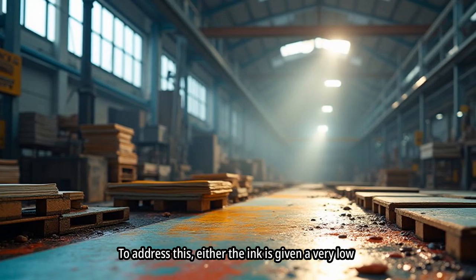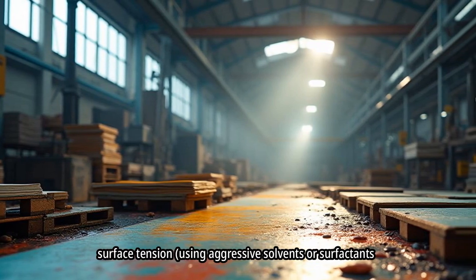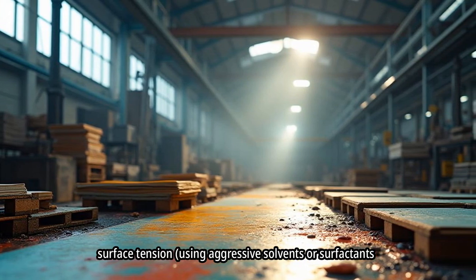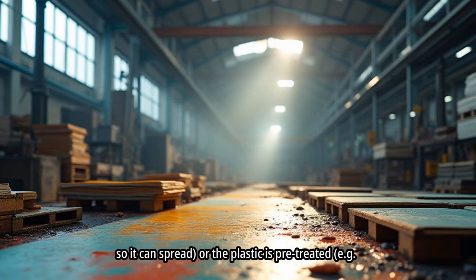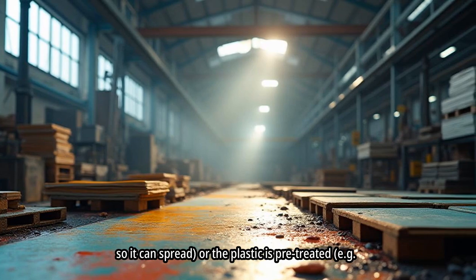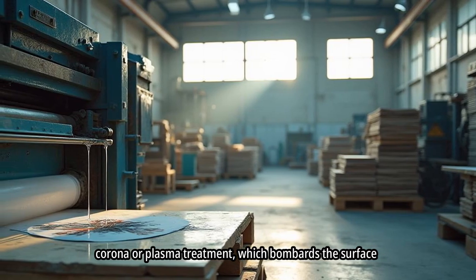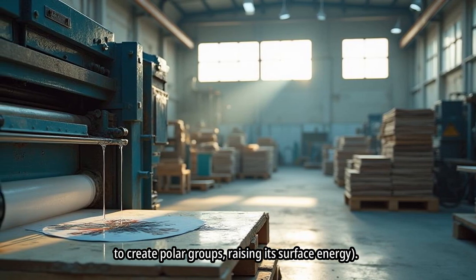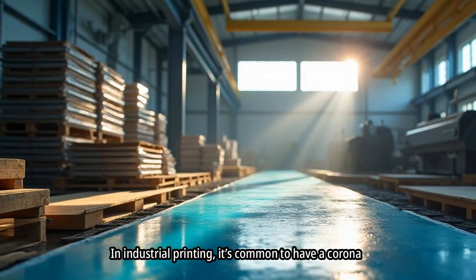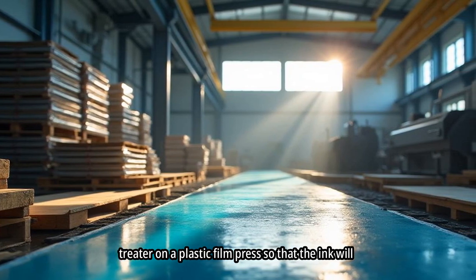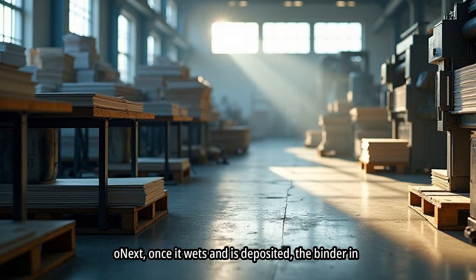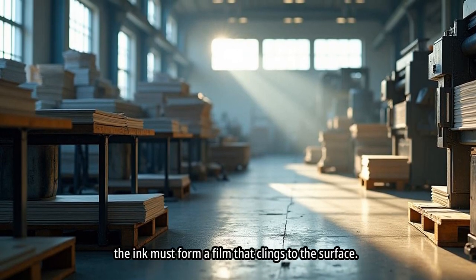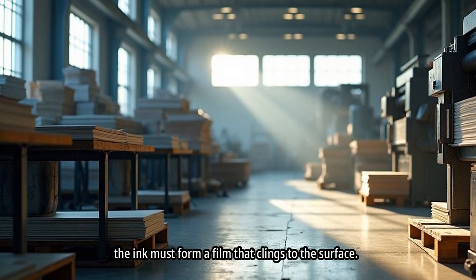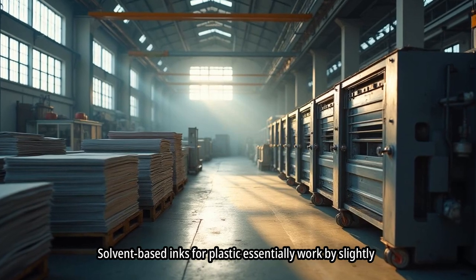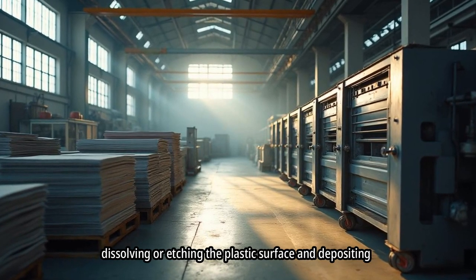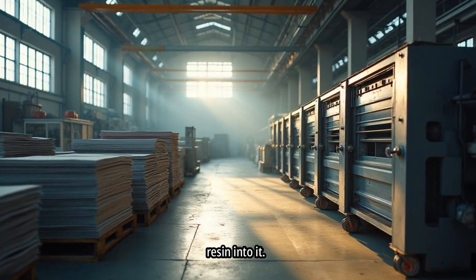To address this, either the ink is given a very low surface tension, using aggressive solvents or surfactants so it can spread, or the plastic is pre-treated, e.g., corona or plasma treatment, which bombards the surface to create polar groups, raising its surface energy. In industrial printing, it's common to have a corona treater on a plastic film press so that the ink will properly wet and stick. Next, once it wets and is deposited, the binder and the ink must form a film that clings to the surface. Solvent-based inks for plastic essentially work by slightly dissolving or etching the plastic surface and depositing resin into it.